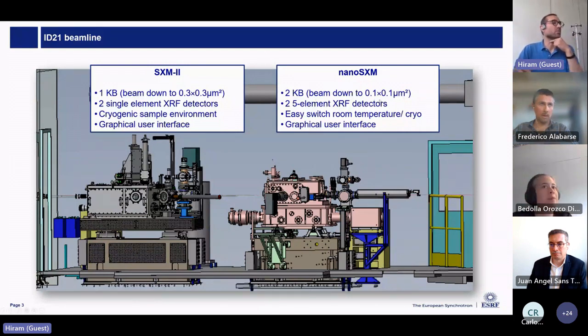And we are just now installing a new microscope, to be able to fully exploit the EBS capabilities, the high flux and the coherence, so that we get a smaller beam spot. With this one, we are expecting to get 100 by 100 nanometer beam size, and we have invested in more stable mechanics, but also in larger detectors, so that we have a better sensitivity. And we have invested also in an easier way to switch from room temperature environments to cryo environments, because the cryogenic sample environment is really one of our particularities of the beamline. And I will explain more in detail why.